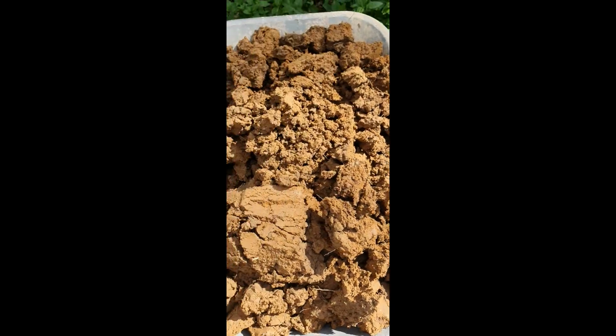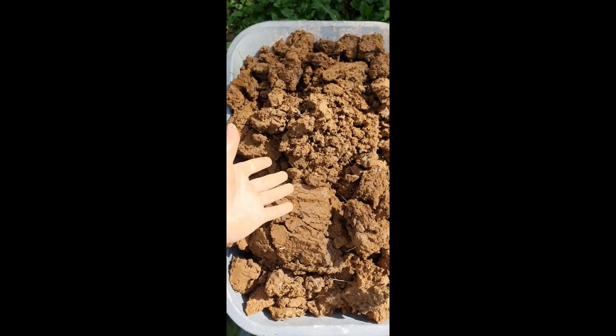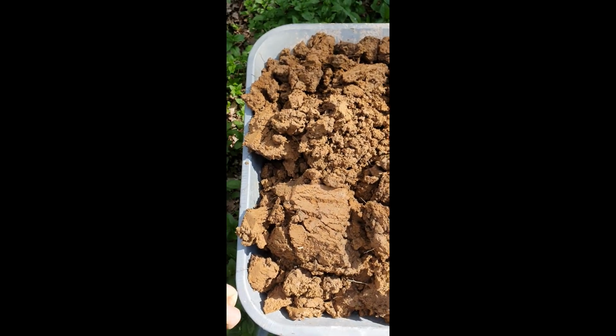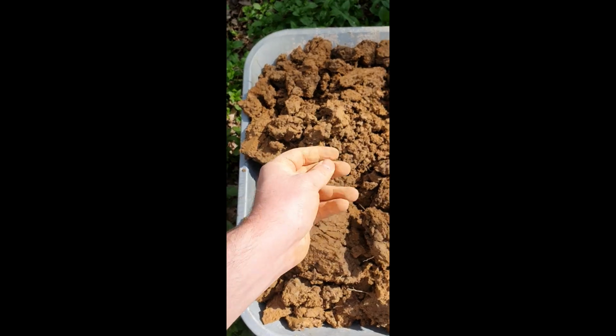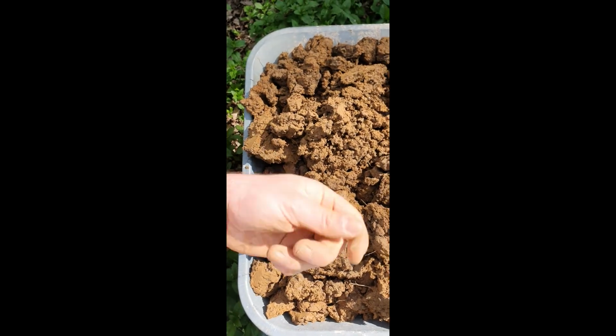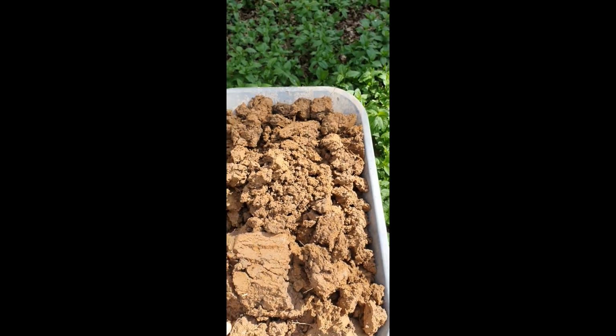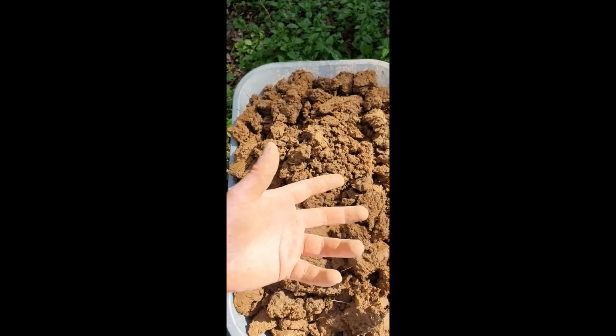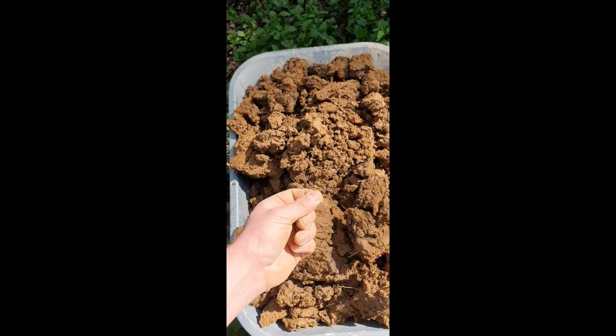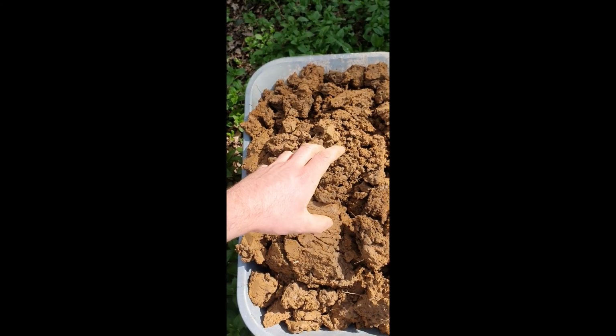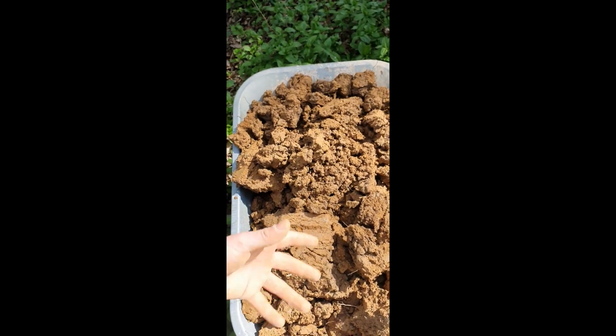But grog, which is pre-fired clay, so terracotta or bits of terracotta pot, is what I'm going to use, ground down very fine into a fine dust and mixed in with the clay. And the good thing about grog is because it's already been fired, it can't shrink anymore. So you mix it in and it stops the shrinkage of the clay and prevents cracks.